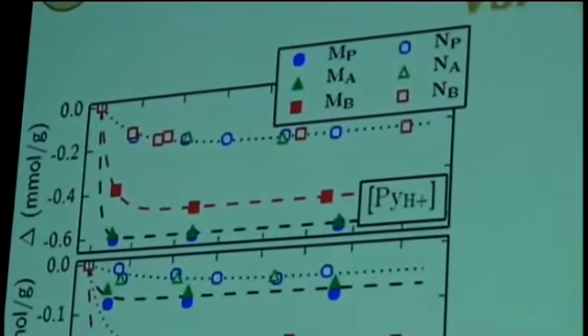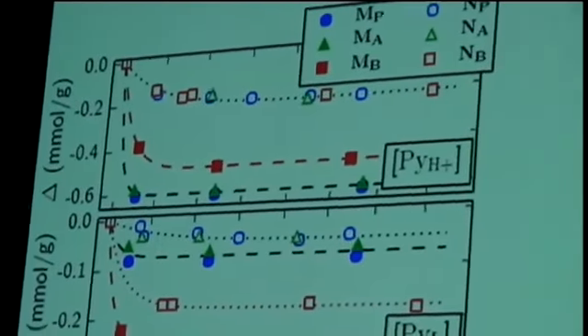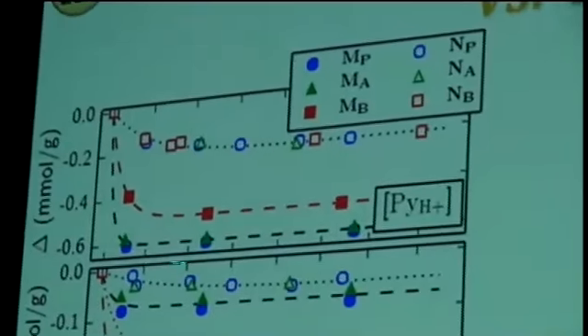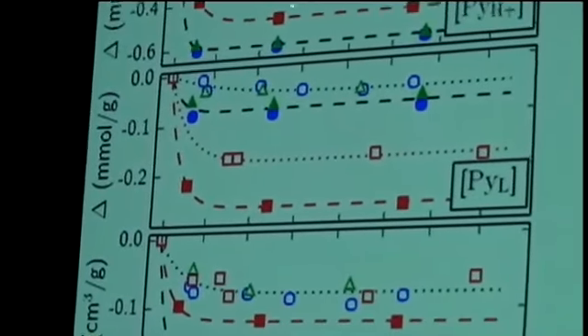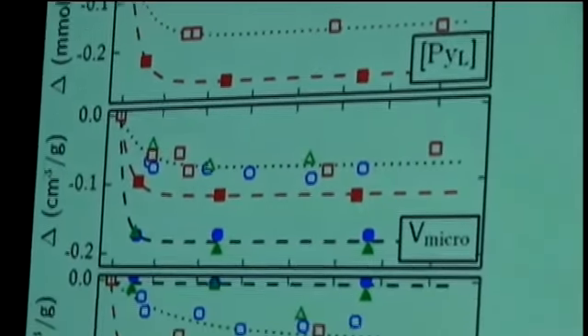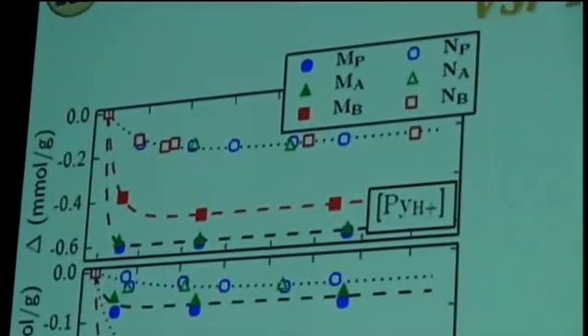Here we show that all the acid sites have been consumed, or the zeolite has been surrounded by coke, preventing the penetration of hydrocarbons. We have the same thing here. The only exception is the micron-sized crystal where some mesopores have been added by caustic treatment. This is the material, by the way, that contains the highest level of coke. So what is important in zeolites is not the quantity of coke, but the location of coke, the toxicity of the coke.